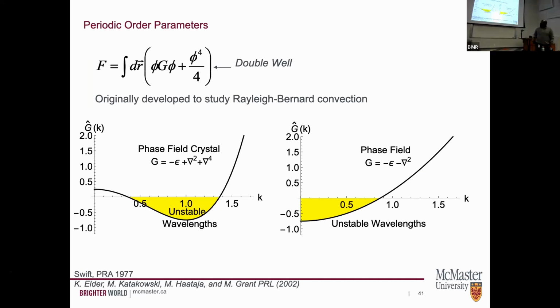And so in one of my previous slides, I wrote an equation that was similar to this, and I said that was the simplest model you could come up with for a phase field model, and I used it for the spinodal decomposition. It turns out that if I change the behavior of this particular kernel, so before it was just a surface term and a constant term, so it was this, a surface term and a constant term. If I do some kind of pseudo-stability analysis, I could find out for my phase field, the only unstable wavelengths are at the long wavelength limit.